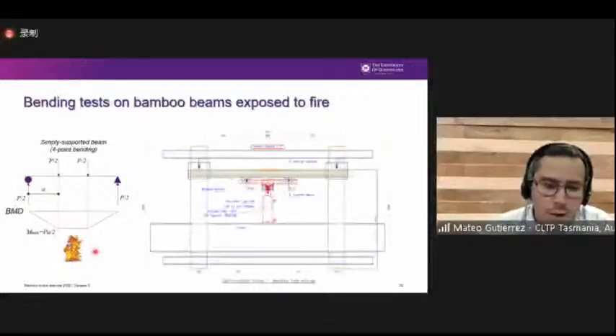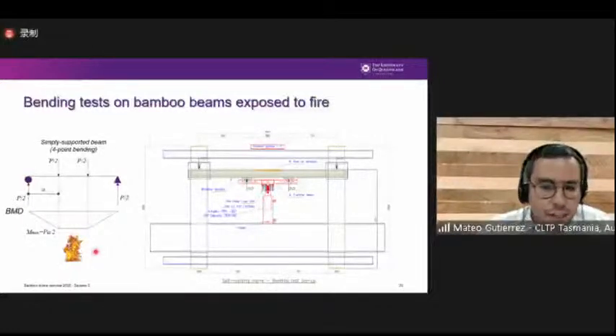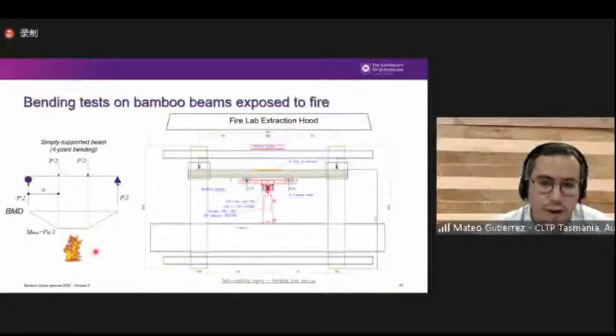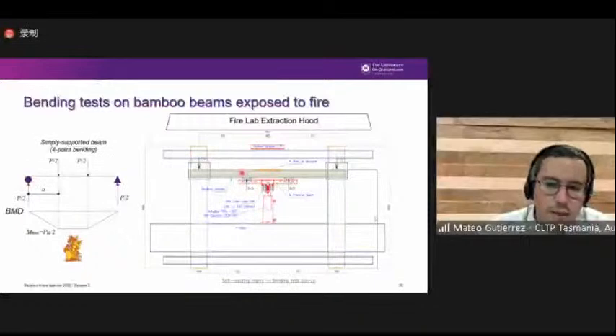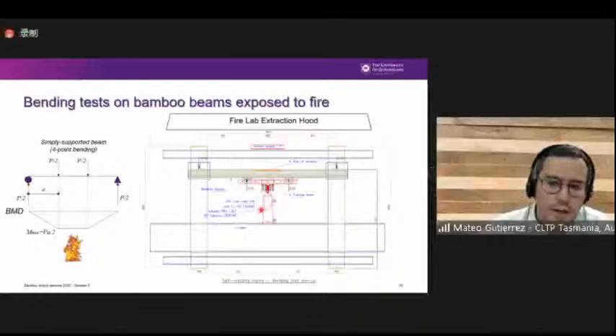So doing a fire test is not an easy task. It normally requires a fire lab, an extraction hood to handle the smoke production, and to also be able to do a safe test, because when you have fire, things can get out of control. And we have to be very careful when testing during fire. So in order to conduct this test, basically we turned around the beam, and instead of testing the beam downwards, we tested it upwards, like to apply the load in the upwards direction, right?